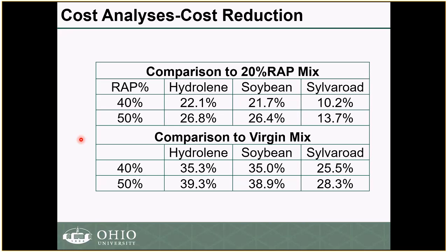You can see that compared to the 20% RAP, you can have a cost reduction of more than 25%. With Hydrolene and Soybean, with the Sylvaroad, it's around 14%. If we're comparing it to the virgin mix, and this is important because, as I said at the beginning, some local public agencies are not using any RAP. It's about 1/3 that are not using any RAP in their mixes. So that comparison, in the second part of this table, is very important for those agencies. You can really go up to close to 40% when you're using a 50% RAP.